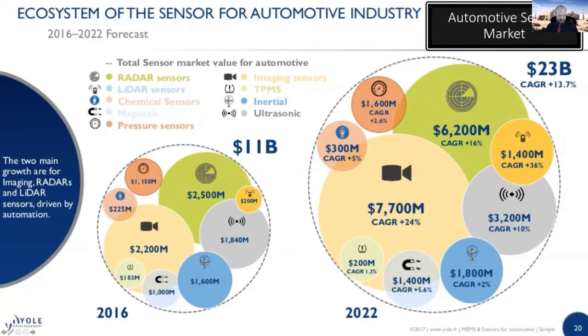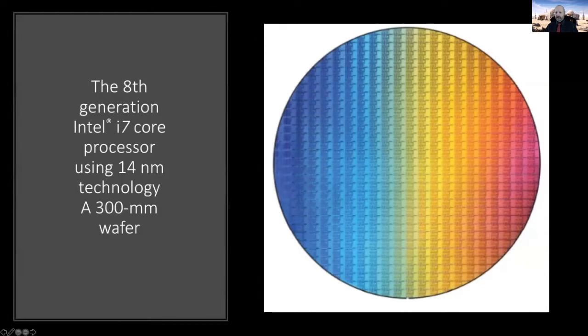All right, so I'll go ahead and next slide. So here you see what a finished fabricated wafer looks like. This is a 300 millimeter wafer, which is about 12 inches. So the history of wafer sizes, you know, if you go far enough back, we started with very, very small wafers, less than an inch. And then we went into production with 1 inch, 2 inch, 4 inch, 5 inch, 6 inch, 8 inch, and then 12 inch wafers. And they're trying to get 18 inch wafers going, but that's extraordinarily expensive, especially the tooling for it.